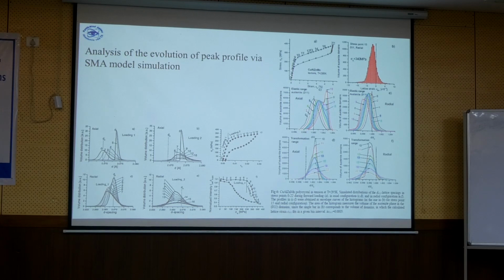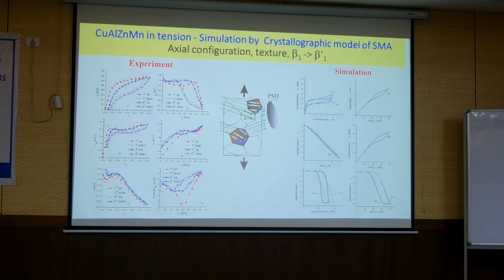If we do repeated cycling, there is one nature which is being observed in shape memory alloy, repeated cycle. The graph will shift. This is actually 2 cycles. So what is the cause of that shift? Stress, internal stress in the material, because we have this everywhere in shape memory alloy. This is much more in nitinol than in this material. If you make the first cycle, you introduce the phase transformation, but also some little plasticity somewhere.